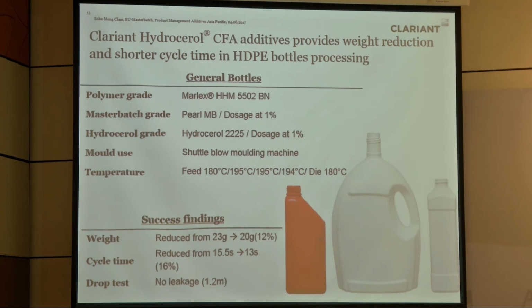There's a weight reduction in this case by using 1%, from 23 grams to 20 grams for the bottle weight. So there's a 12% weight reduction. In terms of cycle time, because less material is being used, the cooling time becomes shorter. So the cycle time becomes 16% shorter. And because of this chemical, it's not just a foaming agent, it's also a nucleating agent. So it passed the drop test. Also no leakages have been found.